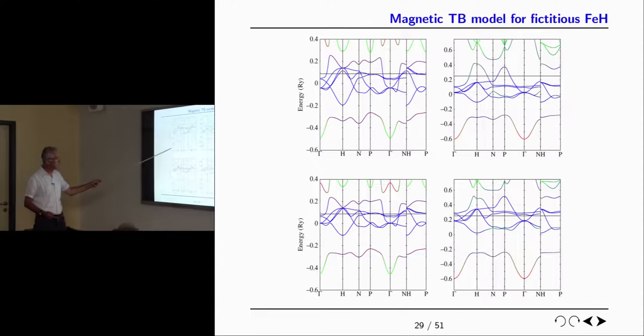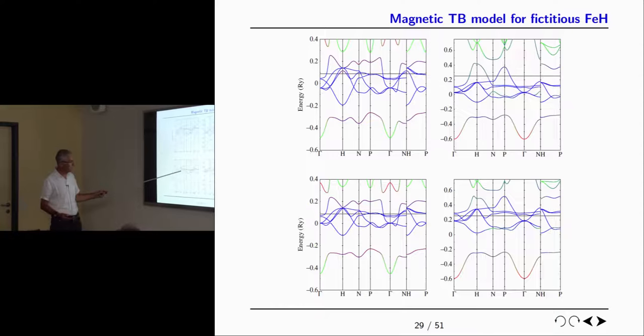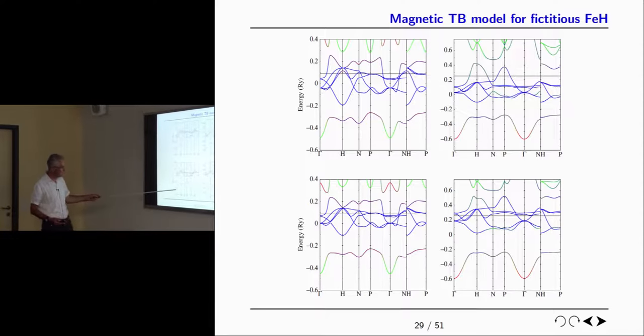But now, the interesting thing is that if you remember the pure iron bands, there was an iron S band, which rose as a free electron band and hybridized and mixed with the D bands. When hydrogen is put onto the lattice, there's an orthogonality between the iron S and the hydrogen S. The iron S are pushed way up out of the picture. They're up above the Fermi level somewhere. So the iron S bands have disappeared. And now we have the hydrogen S bands down here, split off by a large band gap from the D bands of the transition metal.